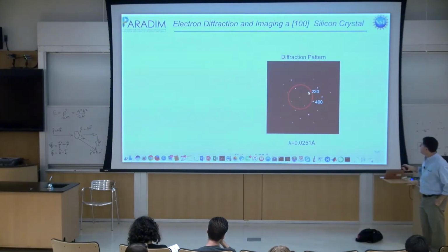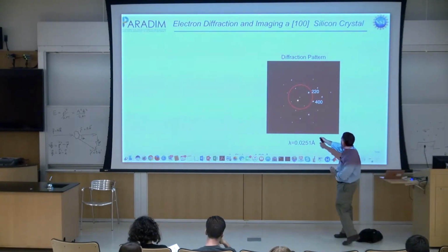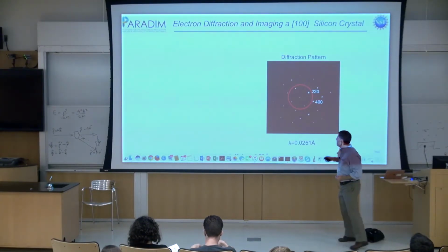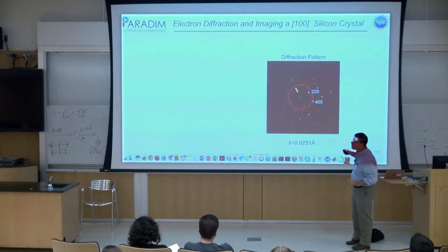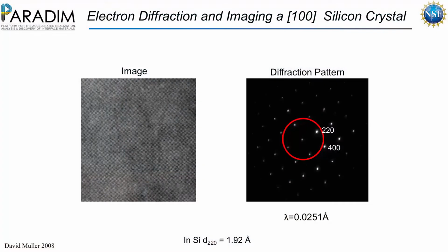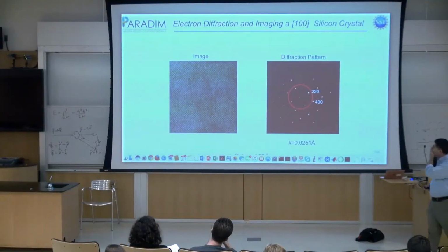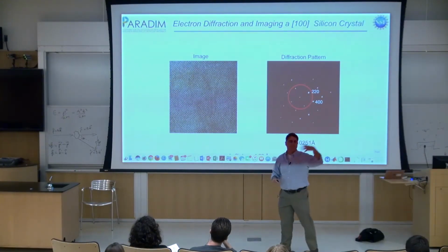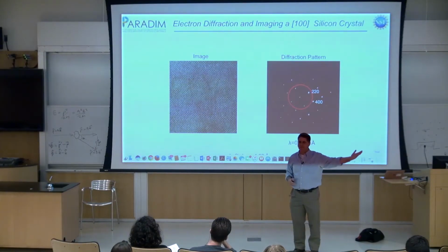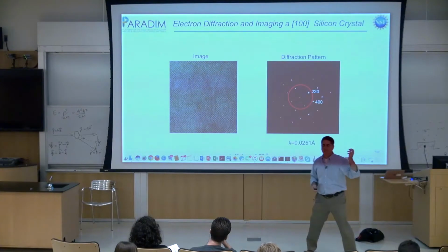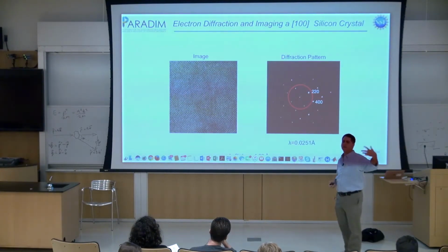But what this tells me is I have one sine wave running in this direction like that, and a second sine wave running in that direction like that. Two sine waves at 90 degrees to each other. And that's the image, two sine waves overlapping. It also happens to be the positions of the silicon atoms down the 100 zone axis. So the sine wave is peaked at the position of the silicon atoms because this is annular dark field imaging, where the scattering is strongest on the column.